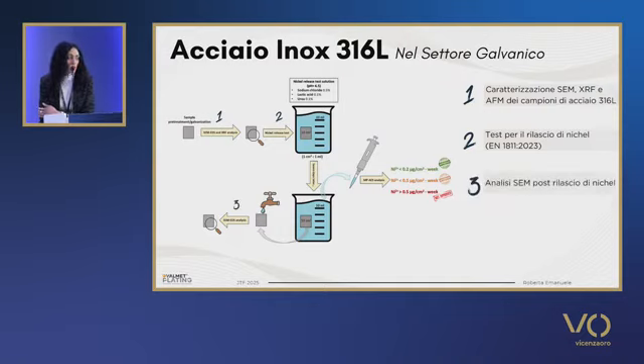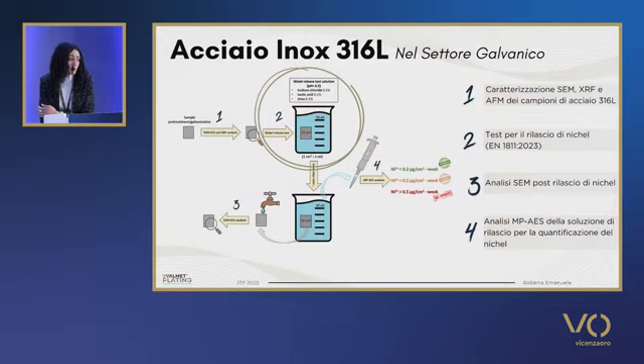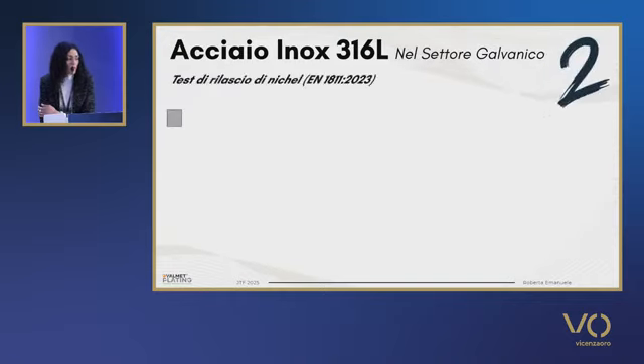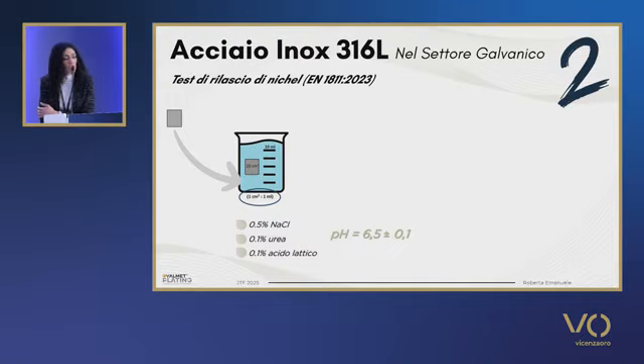After the week of testing, the samples were rinsed and were analyzed with the SEM microscope to look at the amount of nickel released, and the solution has been analyzed with an MP-AES test. Let's have a look at the results of this release test. Based on the legislation, samples are to be cleaned with a solution, and then they should be suspended within a container where a solution of artificial sweat is included with sodium chloride 0.5%, 0.1% of urea, and 0.1 of lactic acid.